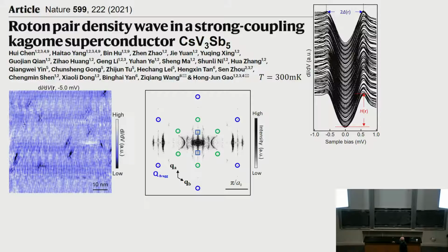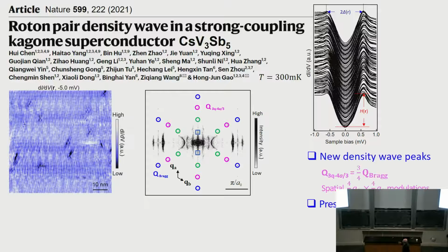And you also see some stuff not very well resolved, the 4a0 thing here. But if you look closely, there are 6 more peaks. I didn't show you a blow-up of that. It's not as sharp as the Bragg peak, but there are definitely peaks there. And they are 3/4 of the Bragg peak. So that's spatial 4a0 over 3 by 4a0 over 3 modulations. And that Q is the Q that connects these pockets.